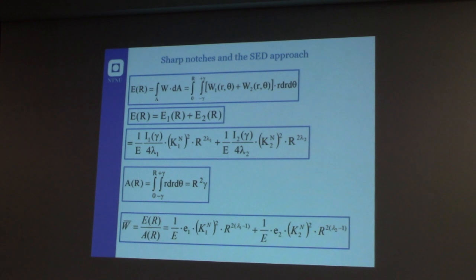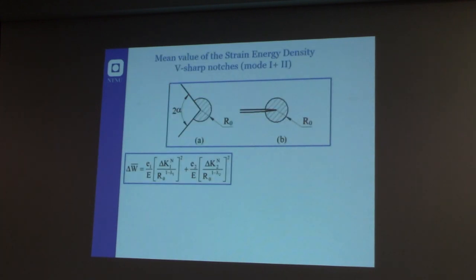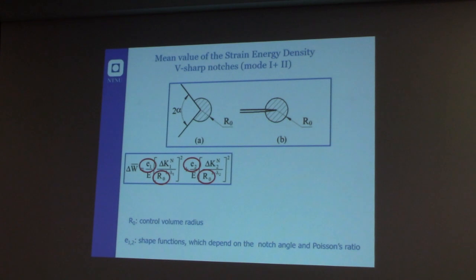So actually it's a more powerful tool, and the advantage is that the strain energy density always has the same unit of measure, independent of the notch opening angle. So you can compare directly a notch with a notch opening angle of 135 degrees and the crack case, for example, without any problem. So you can consider this kind of notch and this crack, and you can always very easily compare the results. R0 is the control volume radius of the material. I will give you the definition later.